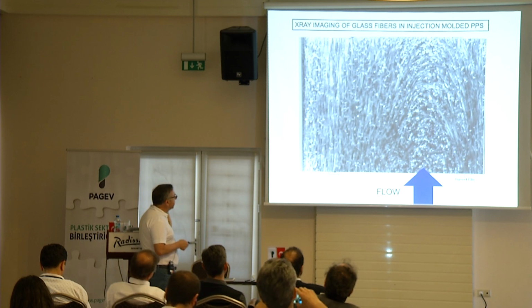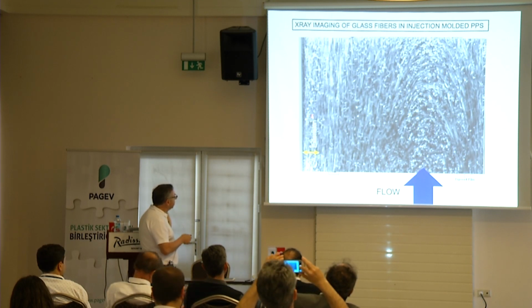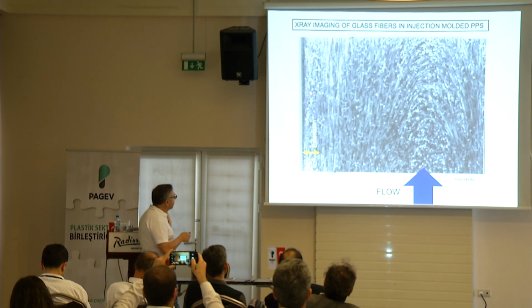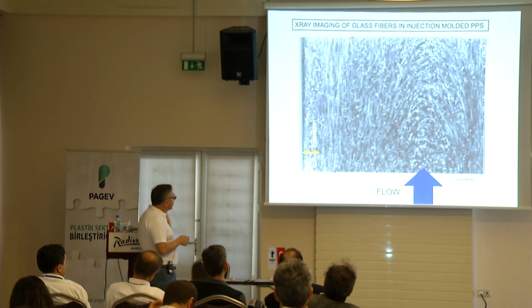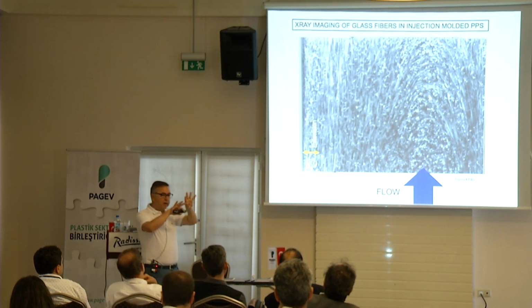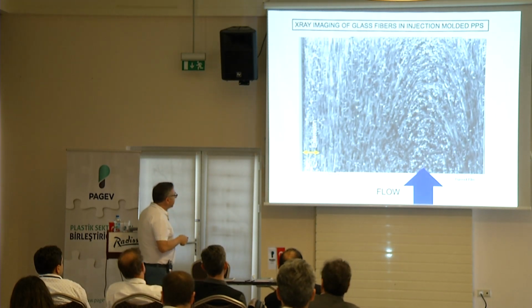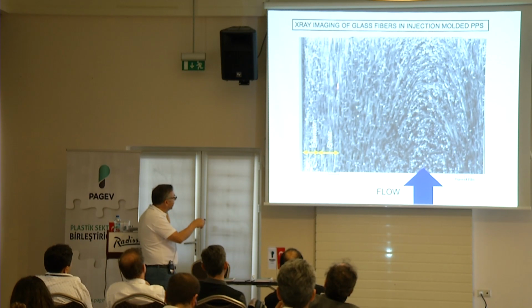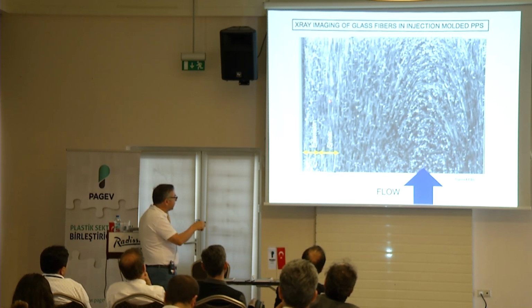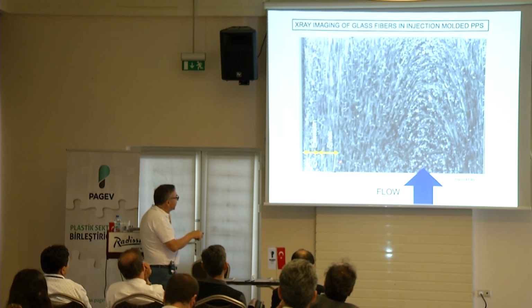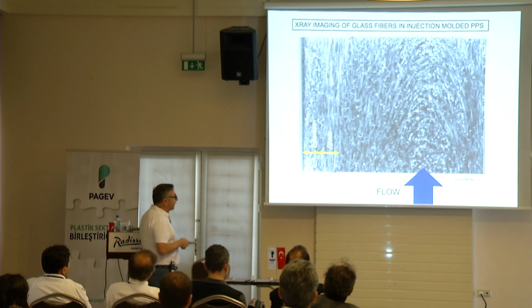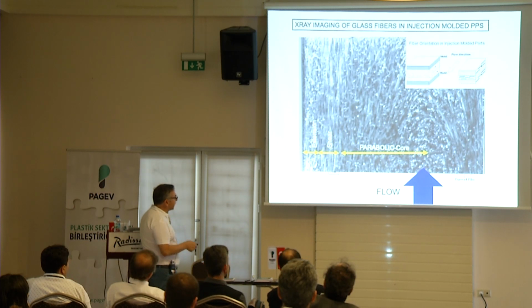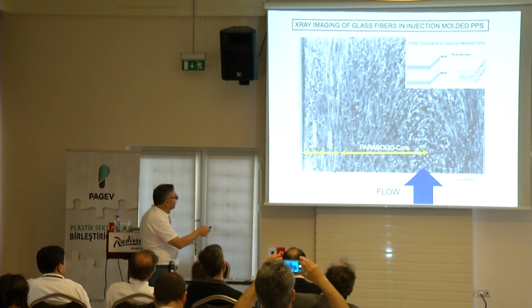So if you look at the close-up, what you see is that dramatically this is an extensional flow. Remember that biaxial flow? The skin layer actually has lots of fibers oriented that way and also pointing towards you. So in the skin, they are not all in the flow direction. What's in the flow direction, this is the flow direction, is this shear layer that we've been looking at. These glass fibers also have a dramatic shear orientation effect. And then in the interior, you basically have a parabolic profile that's frozen in the process. It's following this profile.